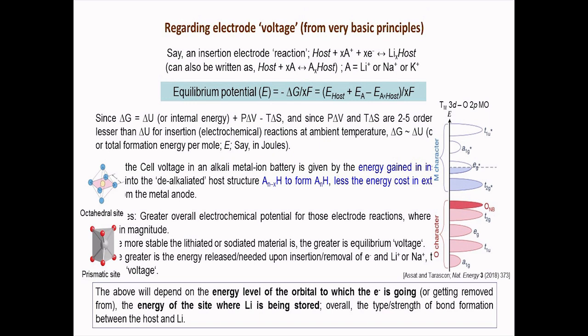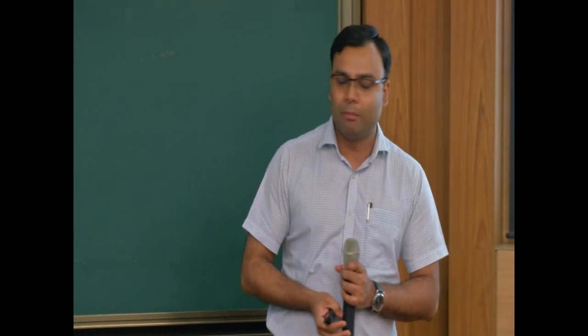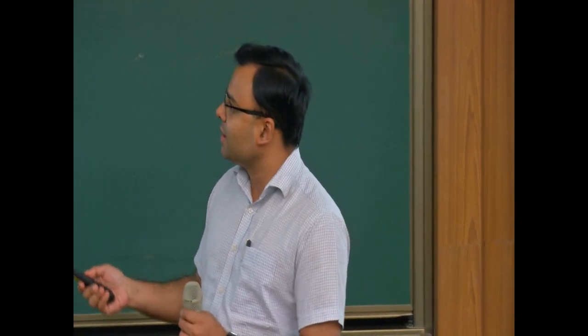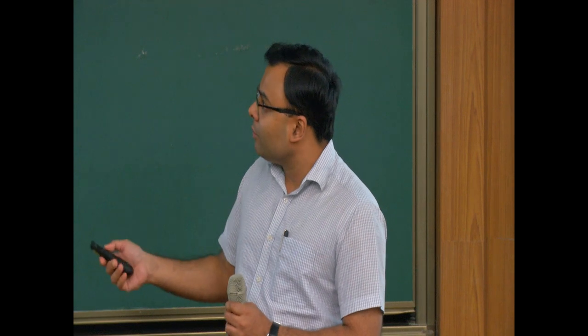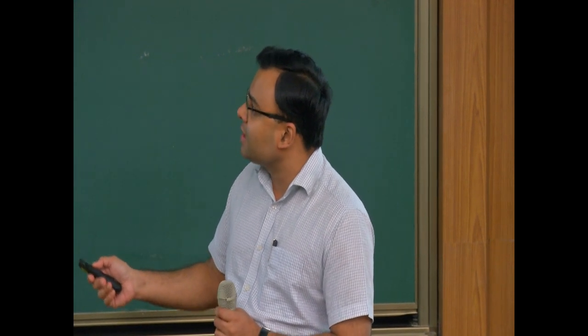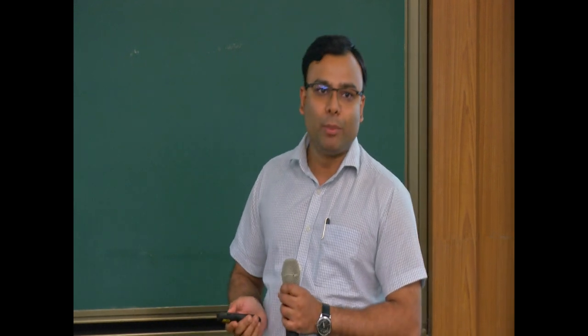Now, talking about that, if one looks into the very basic thermodynamic principles and considers one elementary reaction, like a host in which the lithium ion, which is the A+ here, will get inserted, forming the lithiated host, then the equilibrium potential associated with this reaction will be given as per the Nernst equation by the change in free energy, which can be approximated in terms of the change in internal energy, because the P delta V term becomes negligible compared to the change in internal energy. So overall, it is this change in internal energy which governs the equilibrium potential.